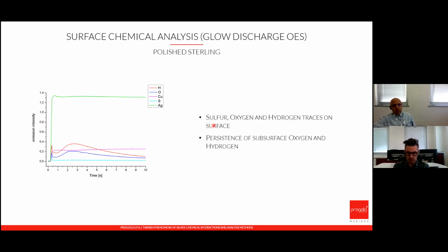Now, we can start with the glow discharge analysis for polished traditional sterling silver after a few days in air. It showed only traces of surface sulfur, oxygen, and hydrogen, revealing the important role of humidity in this process, and some oxygen and hydrogen in the underneath layers, probably residues of the sample preparation.